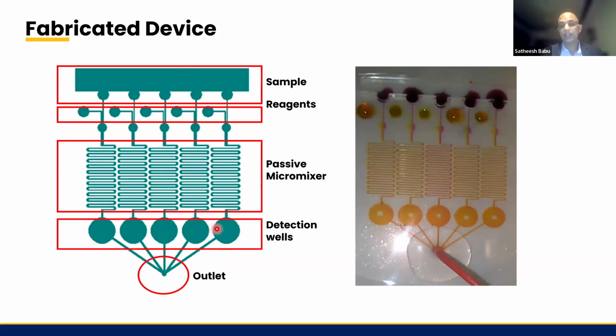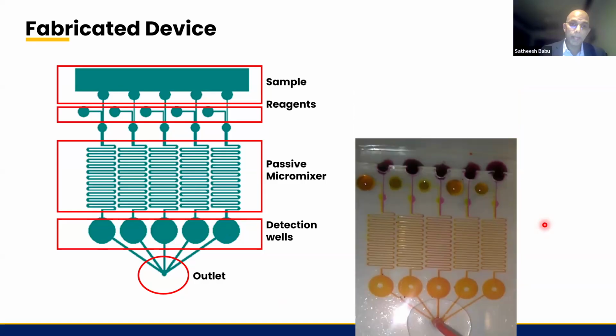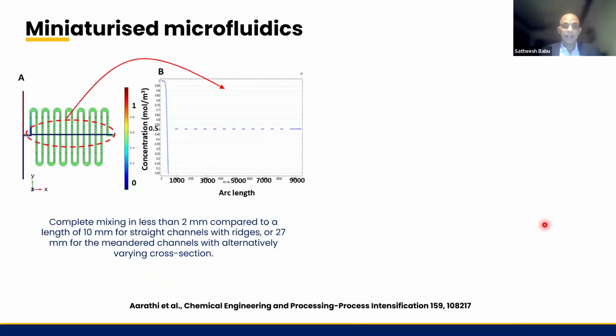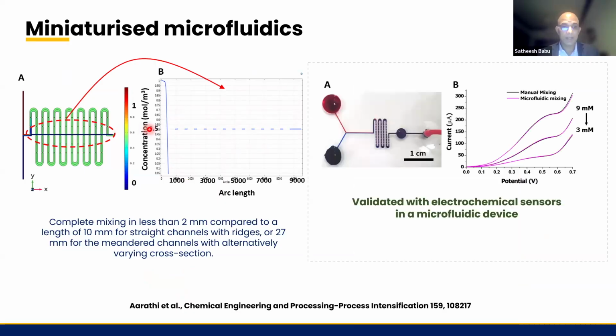So just to understand the mixing, we used colored solutions at first. Then we made the fluid flow. And we could see that when it reaches the sensor well, a complete mixing of A and B, both the colored solutions, was possible. Then to miniaturize the same microfluidic system, we introduced meanders inside the microfluidic channel, so that we could get complete mixing within less than 2 mm distance.